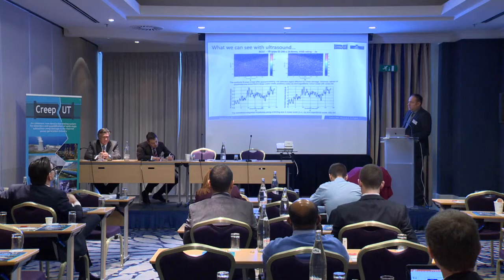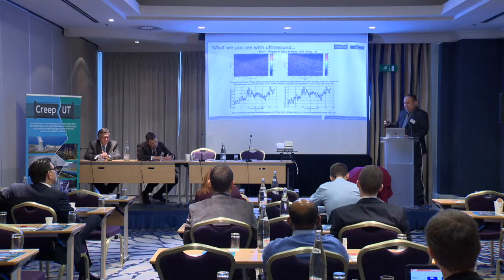So what can we see with this ultrasound: after we made the acquisition of all these things, there is an algorithm and software that analyzes the ultrasound data. We see here things called A scan and B scan, and from the noise level and everything, this will be explained later by Professor Raishutis. We can actually see, after post-processing, the regions that are affected by creep damage, and we can estimate, roughly semi-quantitatively, the state of the heat affected zone that we tested. So we made tests, we made a system, there is software, there is post-processing, and this post-processing can give you reliable results on what is going on with the heat-affected zone in your pipe regarding the creep damage. So it's good.